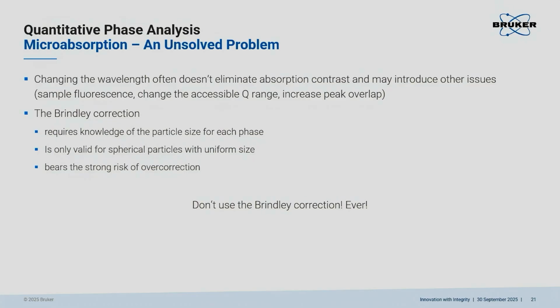How do you get the particle size in your samples? It's not crystallite size, by the way. No? Some people make the mistake of refining the crystallite size and using that in the Brindley correction. That is devastating. If you do that, it is only valid for spherical particles with uniform size.